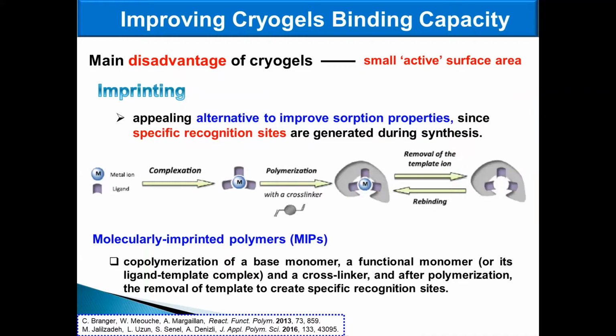Therefore, several approaches to increase the functional surface area without changing the hydrodynamic properties of the cryogel have been developed, including molecular imprinting, surface grafting of ligands, formation of a cryogel within a cryogel, or embedding functionalized particles. Herein is presented, as an example, the molecular imprinting strategy, which is an appealing alternative to improve sorption properties since specific recognition sites are generated during synthesis.